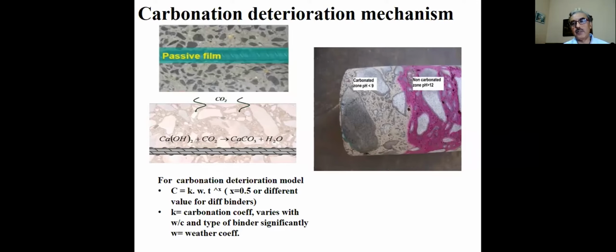If there is a low pH value already in the system because of blended cements with high value of fly ash, say 50% fly ash, the pH level goes down significantly. So there is hardly any protection available to the reinforcement.